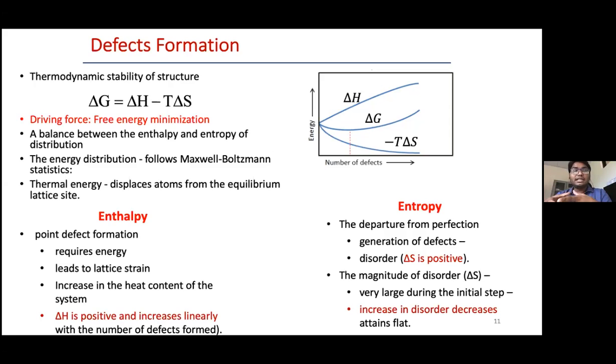And you can see the largest entropy change that takes place is from a very ordered system to the first few disorders, and then when enough number of defects have been nucleated, the disorder somewhat saturates. So somewhere in between, the addition of these two balances, and the entropy changes actually surpass the energy requirements of enthalpy, and you would get a free energy which is negative, and that decides a particular concentration of defects in a crystal. So the thermodynamic stability of these things will govern how many defects will nucleate, what will be their configurational arrangements, and so on and so forth. And so there is a trade-off between these two thermodynamic quantities.